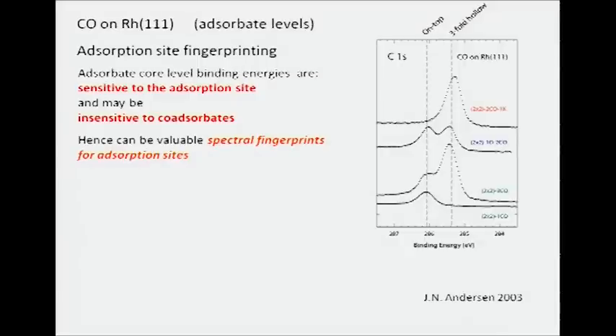Okay, so then finally I just want to say why this problem continues to interest me and come back to the title, which is that if I now try and do some surface science, and this is an example of some data from Jesper Andersen in 2003, although I could have shown you some data that's very much earlier from Niels Martensson on platinum. This is on rhodium. And what we're looking at here is the carbon 1s photoemission from CO adsorbed on the rhodium surface at different coverages. So this is at low coverage, and then we go to high coverage, and two peaks appear.